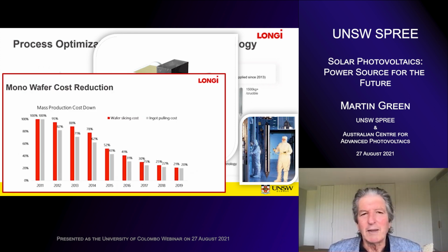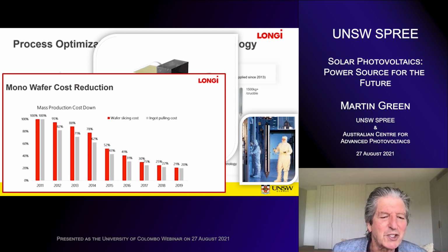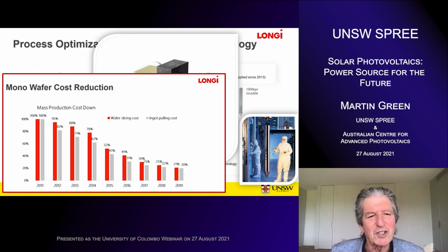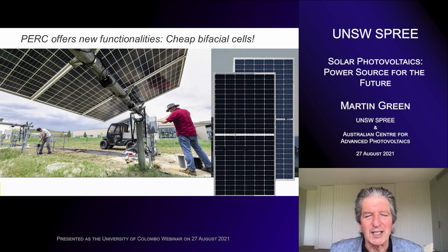So, with the huge uptake of the amount of silicon used in photovoltaics, being able to take the costs out of those processes quite aggressively. So you might be able to read the figures on these graphs, but they're just showing since 2011, so over the last 10 years, the cost reductions that occurred in the cost of making those crystals of silicon and sawing them up. So the wafer is the red region, the sawing operation, and the crystal growth is the grey, but both have reduced to about 1/5 of their value 10 years ago, largely through the increased volume and the increased sophistication of the manufacturing processes and so on.